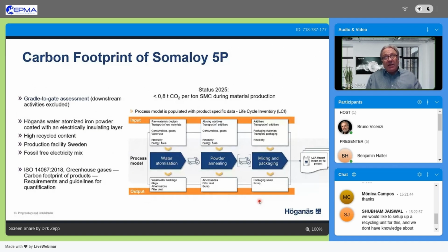But with the activities that we have been doing over the last 2 years already, and this is not only for us, we see the same level from some of our competitors, there is the possibility, and it has been tested also by external auditors, that at the moment at least, we are able to produce 1 ton of SMC material with a CO2 content of about 0.8 tons. And this is, of course, compared to some of the competition materials, especially laminated steel, about 3 times lower than what they have. The reason is mainly the high content of scrap that we're using and the green energy.